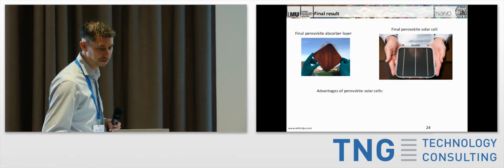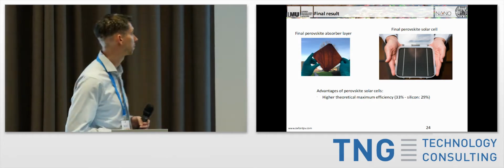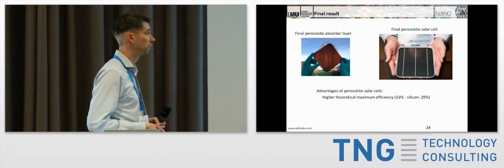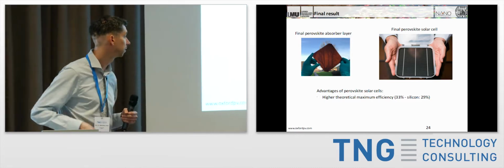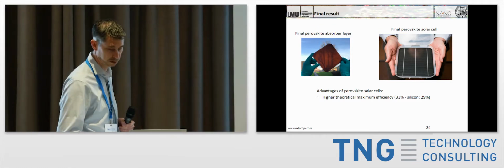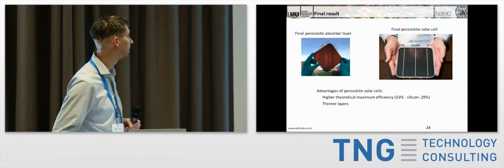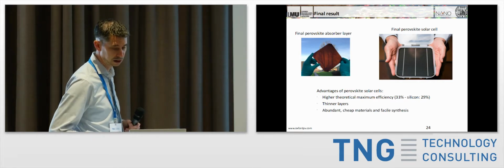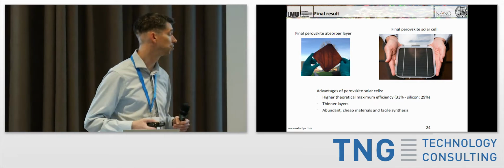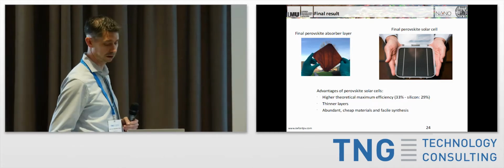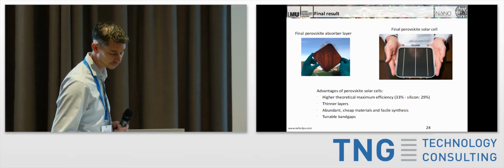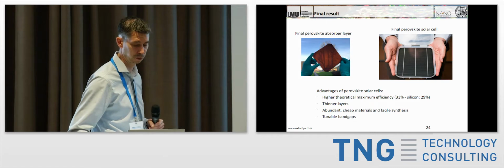All right. What are the advantages of perovskite solar cells? Well, first of all, you can shift the band gap to the optimal position, so you get a higher theoretical maximum efficiency, about 33% with respect to silicon, which can only achieve 29. You can get a lot thinner layers, and the materials that you need for that are abundant and cheap, and this is a lot easier to do than for silicon. And very importantly, you have tunable band gaps.